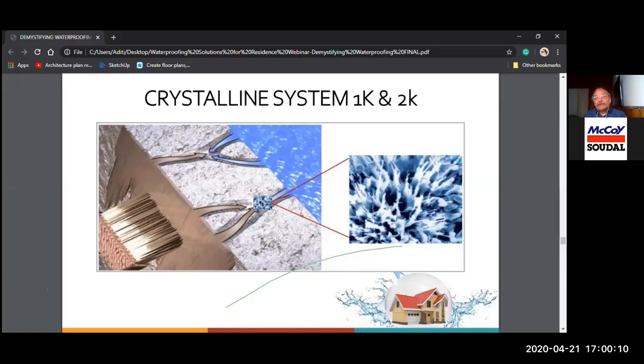So I'll just take one moment. Now, this one component crystalline system is a very good system even while your basement is being casted. When you are about to cast the raft, if you broadcast crystalline system 1K powder, maybe 1.5 to 2 kg per square meter depending on company to company, just before the casting is to be done.